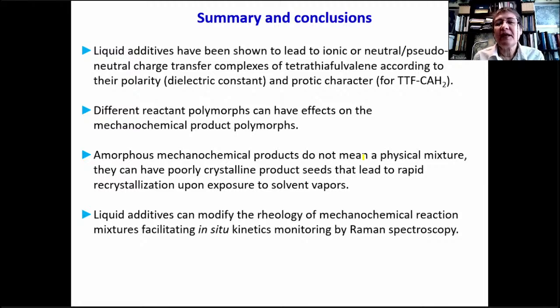So amorphous mechanochemical products do not mean a physical mixture of the reactants, and they can have poorly crystalline seeds of the product that, upon exposure to vapors of solvents, can produce the rapid recrystallization of the products. And liquid additives such as Triton X-100 can also modify the rheology of mechanochemical reactions, and this may be useful to monitor those reactions under homogeneous conditions by in situ Raman spectroscopy.